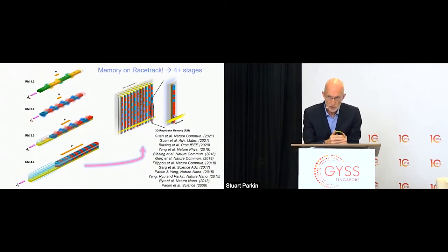In racetrack 3.0, the racetrack itself again is formed from a superlattice of ultra-thin cobalt and nickel layers, but it's deposited on this yellow layer, which is a heavy metal. And this uses a very interesting concept: when you pass current through a non-magnetic metal, which has strong spin-orbit coupling, that charge current will turn into a spin current that flows in a direction perpendicular to the charge current, with a spin polarization which is in a direction perpendicular to both the charge current and the spin current.